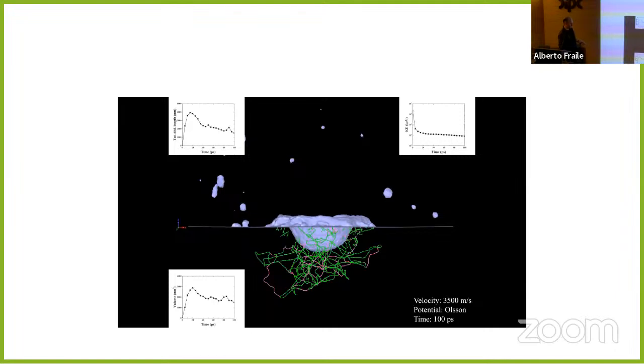So the atoms in the target are removed to observe the dislocations. So we can calculate the total dislocation length in the target. So it goes up, and at about 20 picoseconds, the recombination starts. So all the dislocations will start combining, and finally we have some dislocation forest like this. So there are a lot of things that we could talk about in this. And we can calculate the volume of the crater and much more.